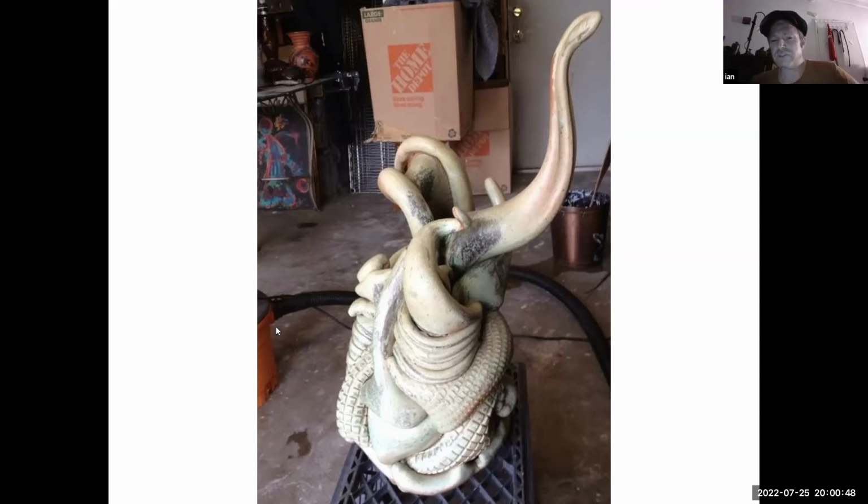So what I'll do is roll the slab in a slab roller and let it true up overnight, so it gets a little bit harder and I can move it around without nicking it so much. Then I'll put a little bit of coconut oil or something on the grid itself, so it's easier to release. And then it's a systematic pressing down of the slab on the roller, because on the pattern, if you get too deep, it'll stick and hold and it really won't pull out. It's hard to explain.